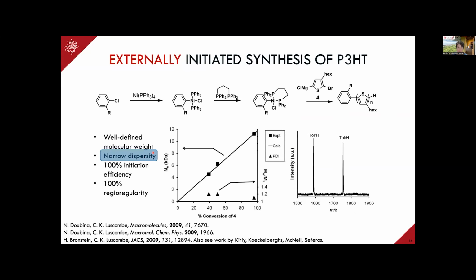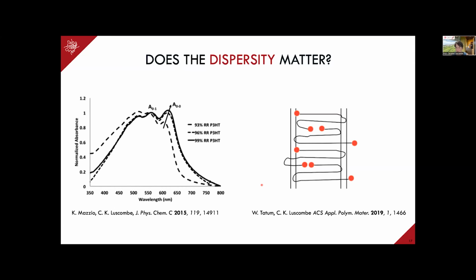Other things that we often get asked is, well, what about the dispersity? Does it really matter if it's a dispersity of 2 versus something lower? And again, in the same study that I just showed, we showed that the dispersity does matter. So a combination of the molecular weight and the dispersity does help to improve the performance. So again, looking at the same picture here, polymers have kind of a natural folding length where they fold. And if the length of the polymer fits the width of the crystal, or if it's exactly double the width of the crystal, or in some cases even triple the width of the crystal, then if we have that molecular weight, and if all the chains have the same molecular weight, we can entirely avoid the end groups being in the middle. And that way we were able to show that we can improve the crystallinity of our materials and therefore improve the charge transport.